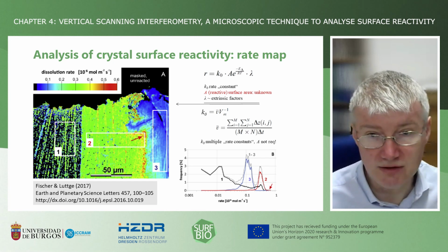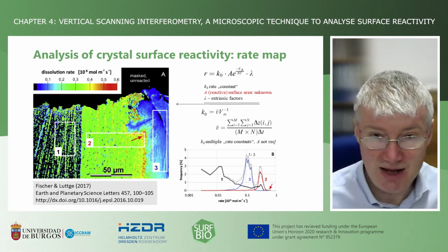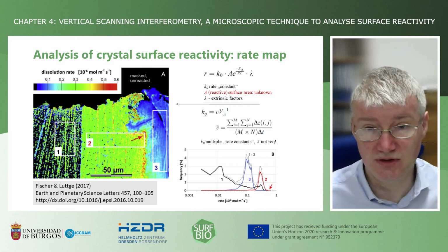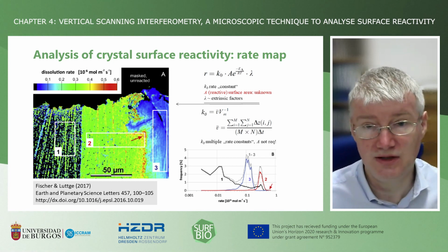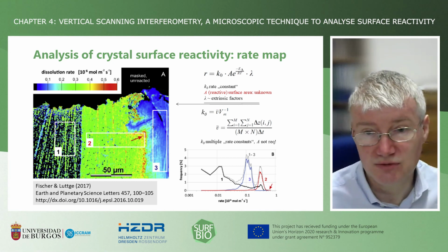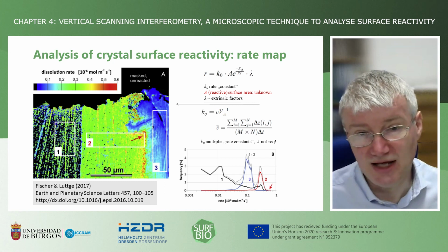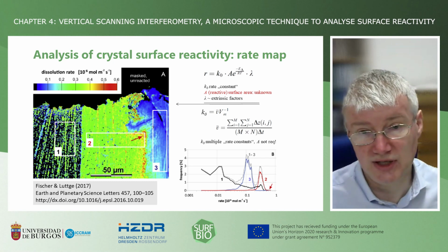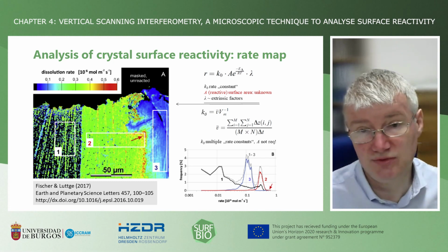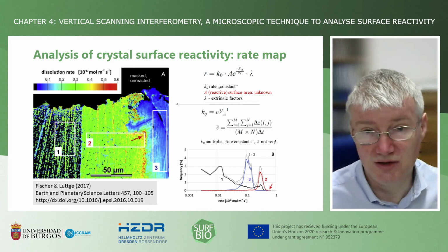All these colors shown here tell you that this chemically identical composition of the material that reacted here shows variability of its reaction rate. And you can identify certain sections with elevated or lowered reaction rates compared to any mean value. Now, with a classical parametrization, we would end up with one single color.